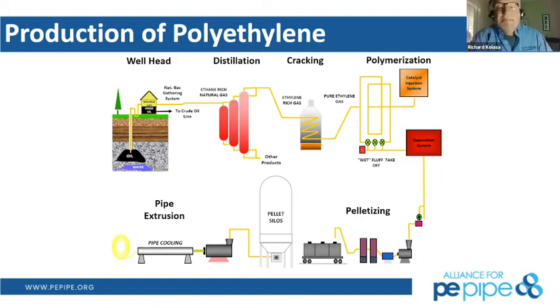Once you produce that polyethylene in its natural state, it's pelletized. Some additives are put in, in very small quantities, 2,000 to 4,000 parts per million, just to protect it for thermal stability, because we're going to heat it up once we get it into our plants, and we're going to remelt it. We want to protect those polymer structures against any kind of degradation via heat. Just like burning your cake or burning your cookies, it's the same principle. You don't want to leave it in too long, but we don't really put antioxidants in baked goods.